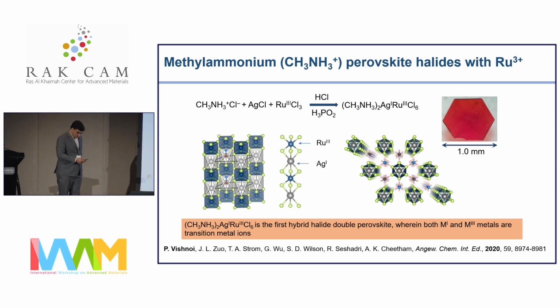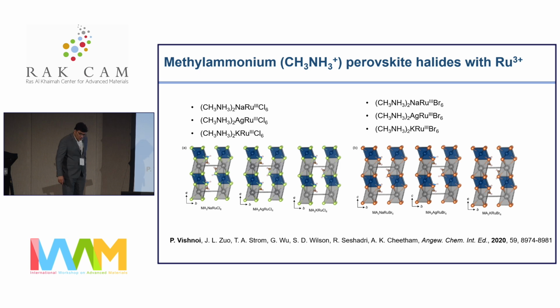This happened to be the very first report on a hybrid halide double perovskite where both the metals were from the transition metal category. So this was kind of a surprise. We didn't know why this was forming 1D, where hybrid double perovskites existed before. So then we went on to change the chemical composition, to see what happens instead of silver, if we use sodium, which is another 1+ metal, or potassium, to see what happens when we change the size.